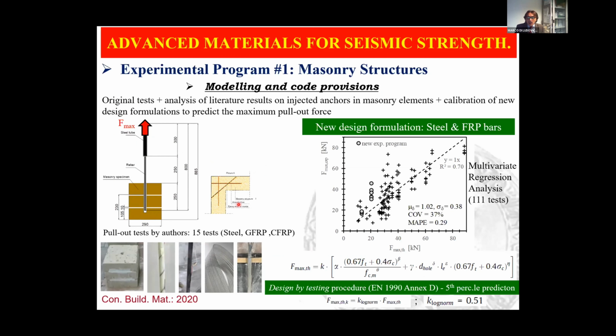And we collected our test results with other available results in the literature, and by using a multivariate regression analysis, we were able to derive a theoretical formulation to predict the maximum pull-out force. And this is the comparison between the theoretical prediction and experimental values. Then, once we achieve this value and a good agreement between theoretical and experimental values, we moved through the design by testing procedure to a 5th percentile prediction force, which is given by this expression.